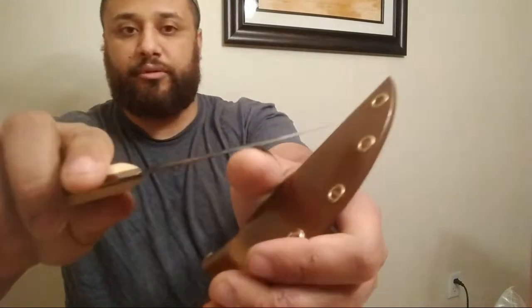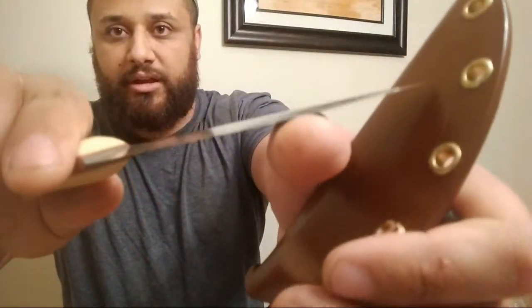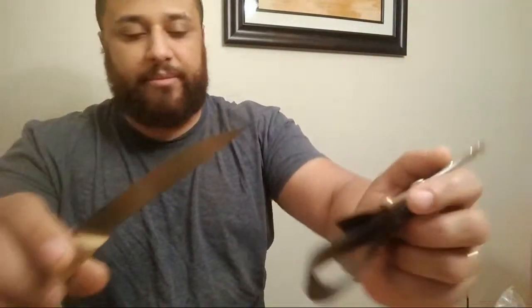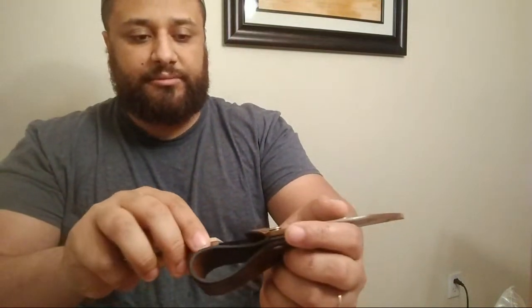For maximum hardness you have to be in the range between 300 and 400 degrees Fahrenheit. What you're trying to do with heat treatment, if you're doing what I'm doing, which is making really thin blades like these, where they're really thin, okay, incredibly thin. The camera can't show you. Is you're trying to get the maximum amount of yield strength inside of the steel, so it'll support the really thin cross-section geometry. When you ask me, like, what's the best heat treat ever?